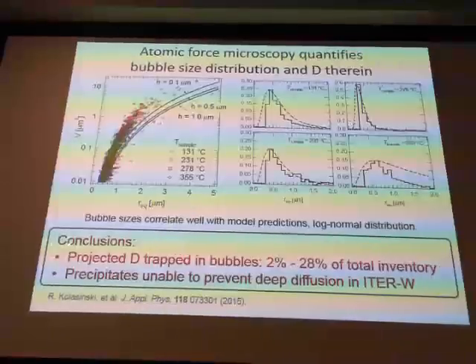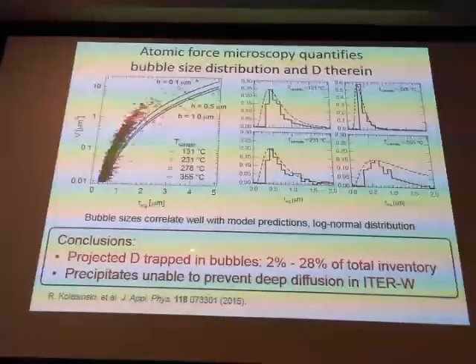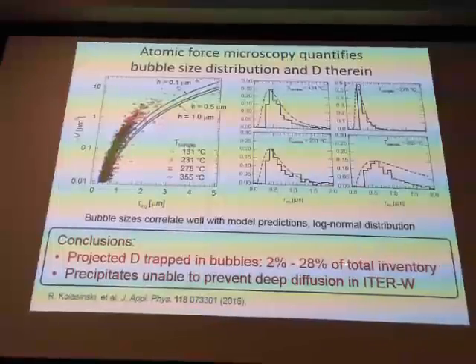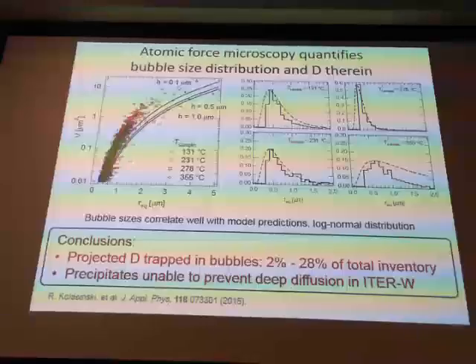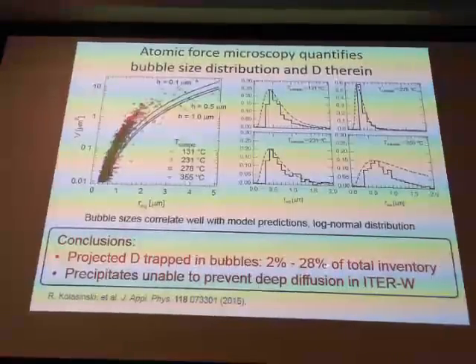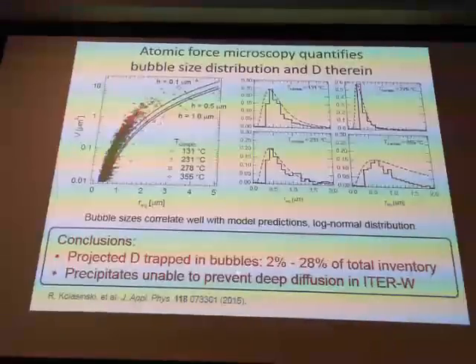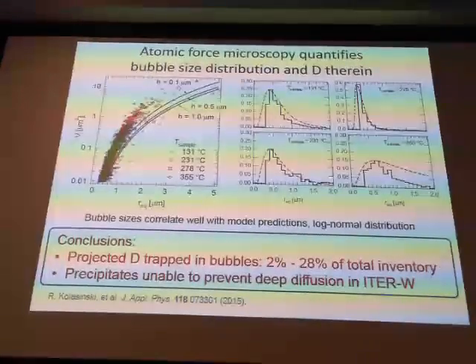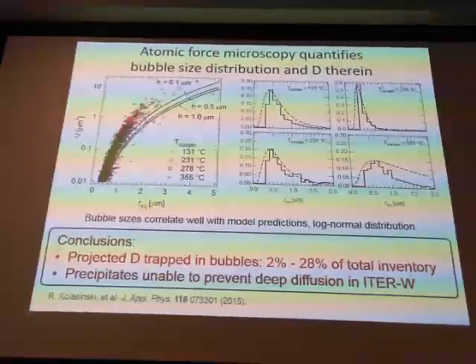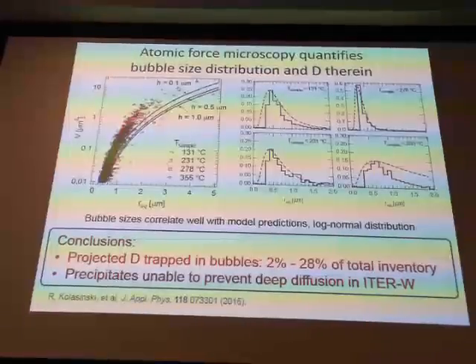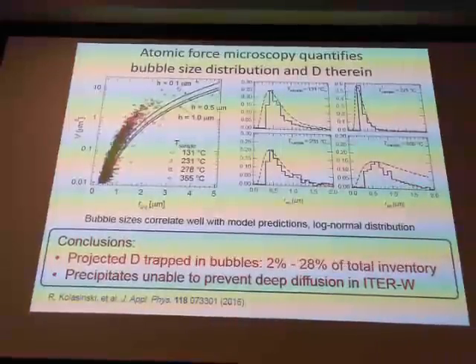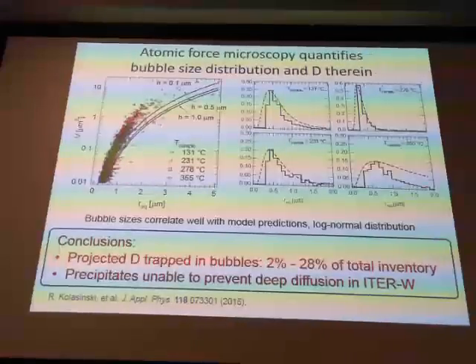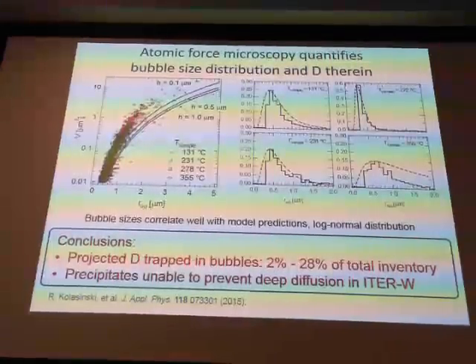So, the main conclusion from this, though, is we wanted to see if this would be enough to significantly affect the total inventory of tritium within the material, and how much would it affect diffusion into the deeper traps that might be present within the material. And actually, it's a relatively modest effect. Maybe 2 to 28% of the total inventory would be in these high pressure bubbles. And in the ITER grade tungsten case, it was unable to prevent deeper diffusion into the ITER grade tungsten. So, just strictly hydrogen exposure wouldn't necessarily have such a strong effect on what you would expect for the tritium inventory as a result of this exposure. But combined hydrogen-helium exposure can have a much stronger effect.